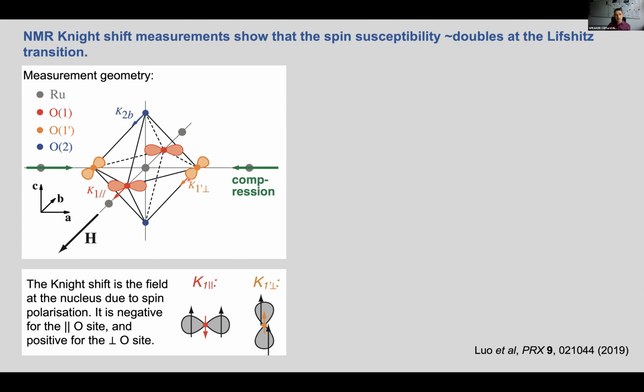These oxygens, it's opposite. The p orbital is aligned with the field, so when they polarize, their dipole fields create a field that is aligned with the applied field. It sees a positive Knight shift.